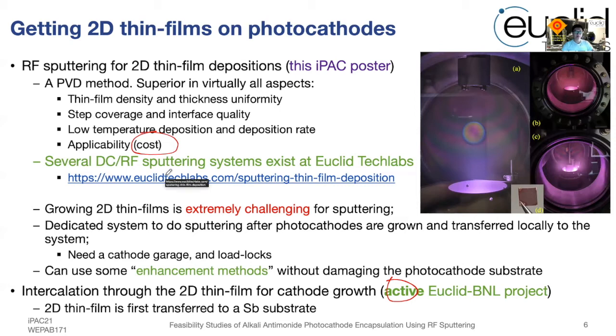Although RF sputtering has so many superior properties, growing 2D thin films in general is extremely challenging, and for sputtering too. So we developed a dedicated system in order to avoid any other contamination and also to satisfy the UHV requirements for photocathodes. For this system, we also need a cathode garage and load locks. And we also took those into account.